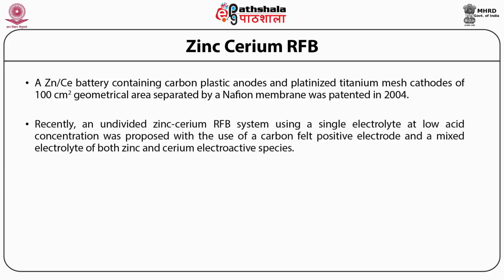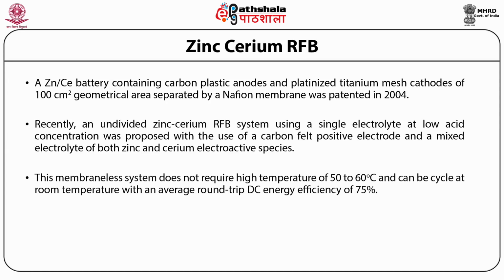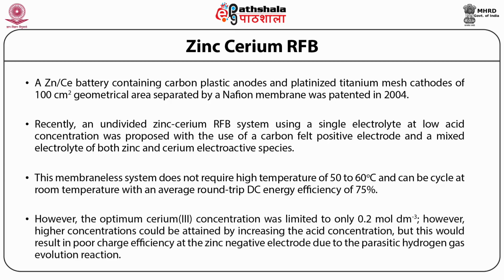Recently, an undivided zinc cerium RFB system using a single electrolyte at low acid concentration was proposed with the use of a carbon felt positive electrode and a mixed electrolyte of both zinc and cerium electroactive species. This membraneless system does not require a high temperature of 50 to 60 degrees Celsius and can be cycled at room temperature with an average round trip DC energy efficiency of 75%. However, the optimum cerium-3 concentration was limited to only 0.2 mol dm⁻³.